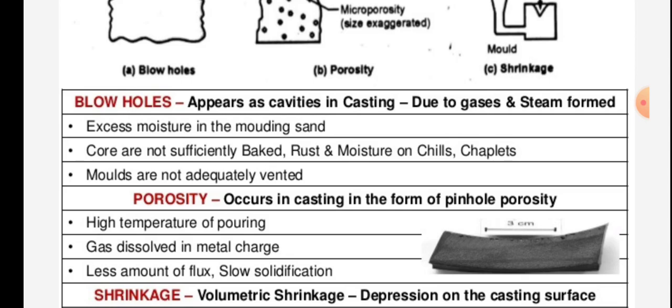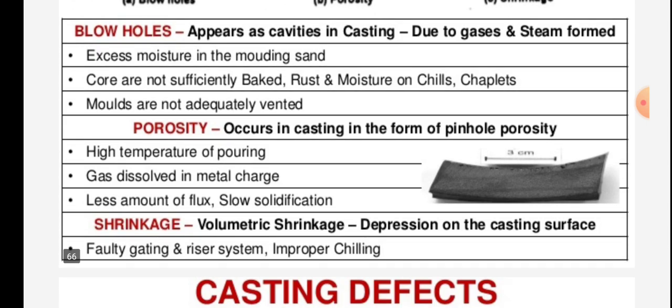Porosity occurs in the casting in the form of pinhole porosity. Its causes include high temperature of pouring, gas dissolved in the metal charge, less amount of flux, and slow solidification.